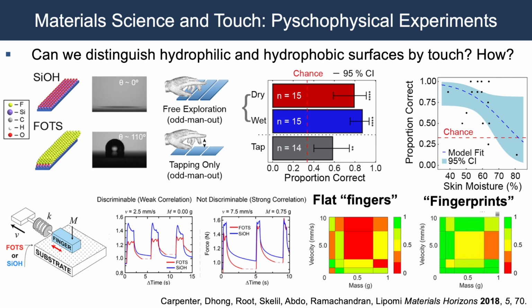And he took all of the data under all of the conditions and produced these discriminability matrices. And what this tells you is that where these squares are green and yellow, we found that they had different friction behavior compared to when you take the oxidized versus the silanized surface. The friction behavior was different, and therefore you should be able to differentiate the surfaces. Whereas where the discriminability matrix shows red, they were very similar to each other, and therefore they would not be able to be distinguished.